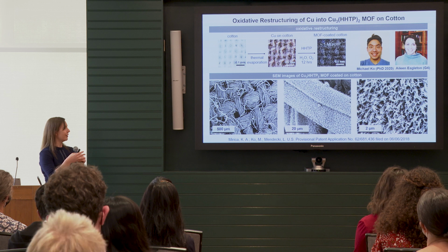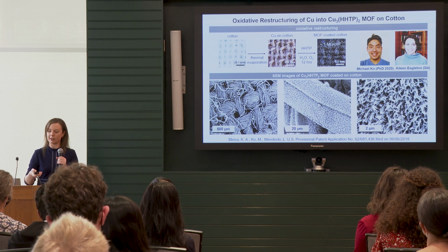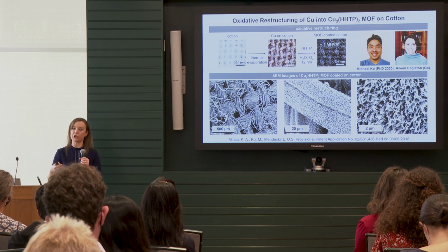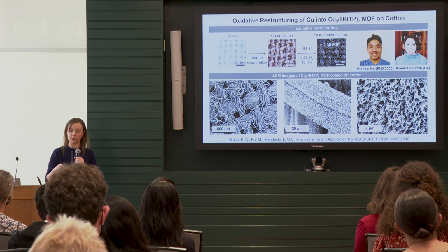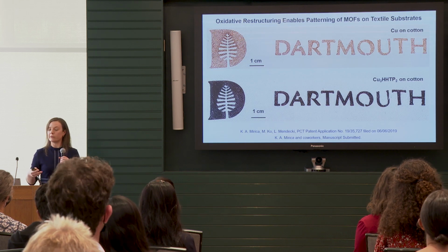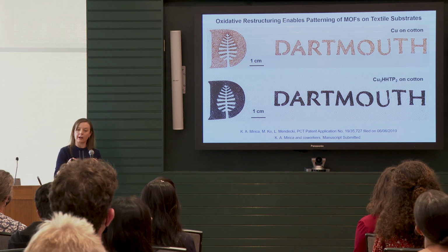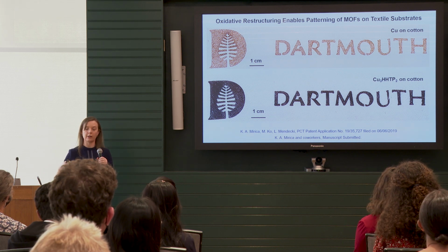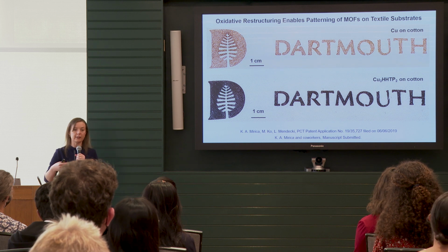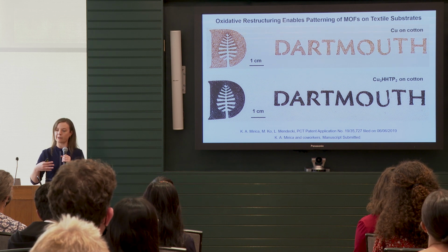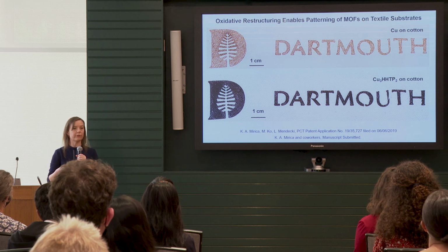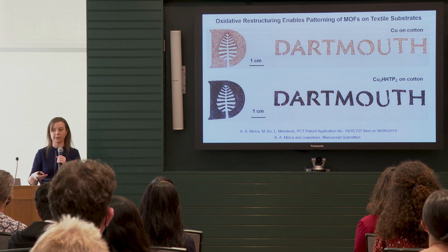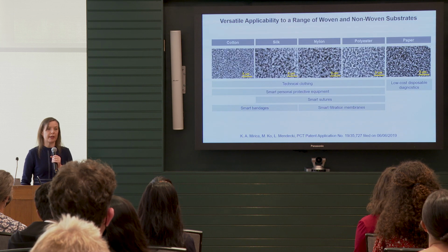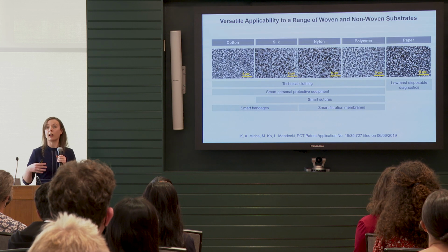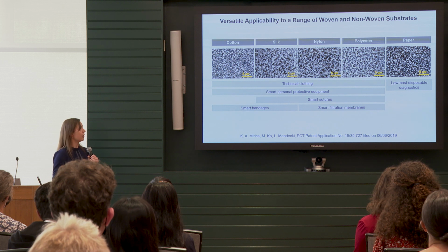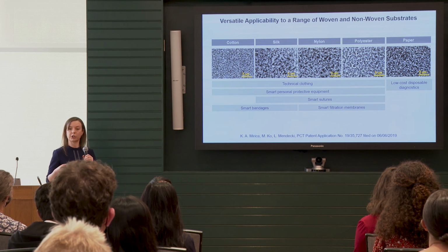But since this discovery and further investigation, we have noticed some really unique features of this particular deposition method or device integration method, one of which is patterning. We can pre-pattern copper on a textile and then convert it with very good fidelity to the pattern of our metal organic framework. So that's useful for potentially patterning materials and devices. We also can extend this method to a range of different substrates. It's not limited to cellulose-based cotton, but can also work on silk, nylon, polyester, and paper.